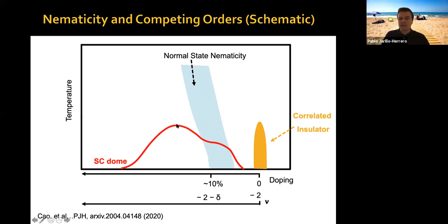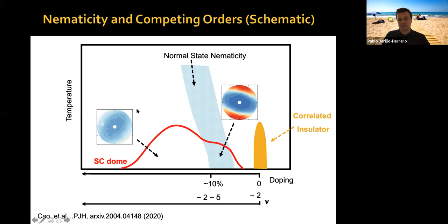Separately, everywhere in the superconducting dome, there is nematicity in the superconducting state. Now this nematicity in the superconducting state seems to be of different origin to the nematicity in the normal state, because it happens everywhere in the superconducting dome, including regions where in the normal state there doesn't seem to be nematicity above it. However, it's important to note that the nematicity axis, the orientation of this ellipse, changes direction. In particular, the major axis changes direction most dramatically. It wiggles a little bit around here, but it changes rapidly and very strongly in this region.